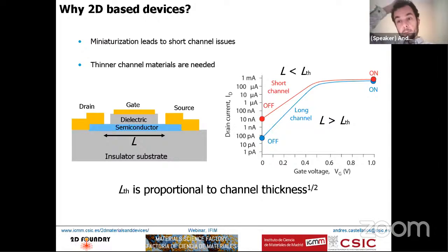Okay, well, thank you, one of the things, very nice talk. Yeah, thank you. So one of the things that we really changed as well, apart from the intrinsic properties of the material, is that we are changing the way the material interacts with traps, because we are observing this crossover from photoconductive to photogating effect. We don't know the microscopic mechanism behind it, but we know that this is happening, and it's telling us that for some reason, when we apply tension, the holes don't get trapped in these mid-gap states. And when we apply compressive strain, these holes get trapped quite efficiently in these traps. So apart from the intrinsic things, some properties are changing also with the strain. So it's quite complex.